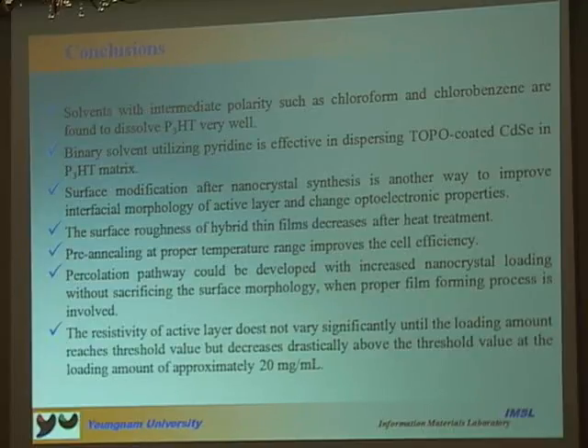And finally, the resistivity of the film does not vary significantly until the loading amount reaches a threshold value but decreases drastically above the threshold value, at a loading amount of approximately 20 milligram per milliliter. My talk is now finished. Thank you for your kind attention.